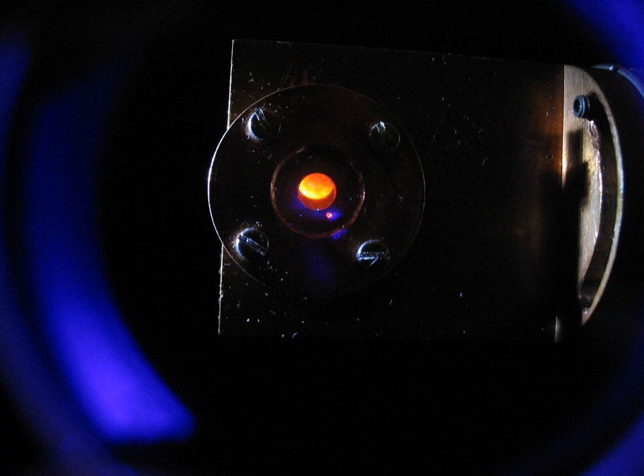Though as an alpha emitter, 244-Cm requires a much thinner radiation protection shielding, it has a high spontaneous fission rate, and thus the neutron and gamma radiation rate are relatively strong. As compared to a competing thermoelectric generator isotope such as 238-Pu, 244-Cm emits a 500-fold greater fluence of neutrons, and its higher gamma emission requires a shield that is 20 times thicker, about 2 inches of lead for a 1 kW source, as compared to 0.1 inch for 238-Pu. Therefore, this application of curium is currently considered impractical. A more promising application of 242-Cm is to produce 238-Pu, a more suitable radioisotope for thermoelectric generators such as in cardiac pacemakers. The alternative routes to 238-Pu use the reaction of 237-neptunium, or the deuteron bombardment of uranium, which both always produce 236-Pu as an undesired byproduct, since the latter decays to 232-U with strong gamma emission.